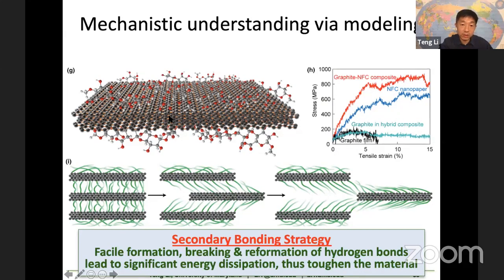When you try to deform and fail this composite material, we know that the few layer graphite is actually very strong and they won't break easily. So what happened is it's a relative sliding, but all these graphite flakes, they are wrapped around with the cellulose nanofibers. So you have a lot of this similar deformation mechanism, the hydrogen bond formation, breaking and the reformation. And we call this secondary bonding strategy because although these secondary bonding are not as strong as their primary bondings, ionic, covalent, metallic bonds, but they can easily form, break, and then reform and lead to significant energy dissipation, therefore toughen the material. And this is also verified by the simulation result as well.